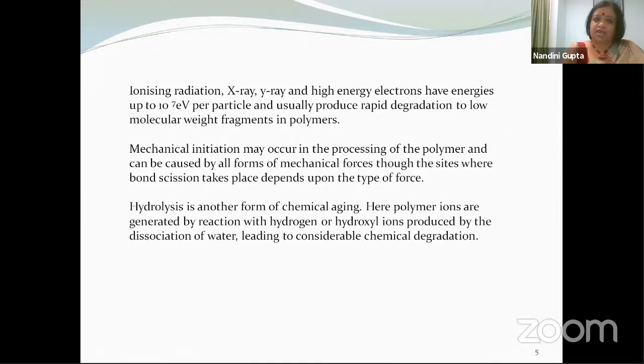Ionizing radiation, X-rays, gamma rays, high energy electrons, have very high energies, as high as 10 to the power 7 electron volts per particle. Therefore, if you place a dielectric in an environment where it is exposed to various kinds of radiation, it is very natural for the polymers to break up into fragments. Instead of long chain polymers, you would have polymer radicals, or even if reactive radicals are not formed, you would have small chains. Once you have small, fragmental chains instead of a long polymer chain, the material will lose its properties considerably.